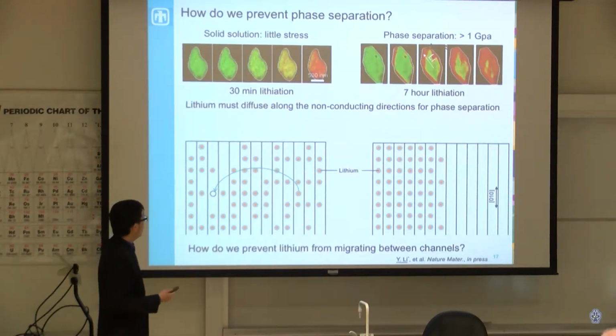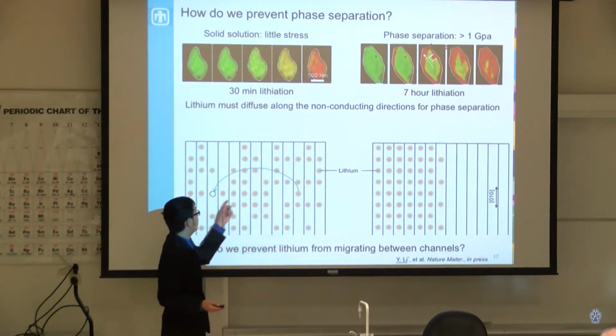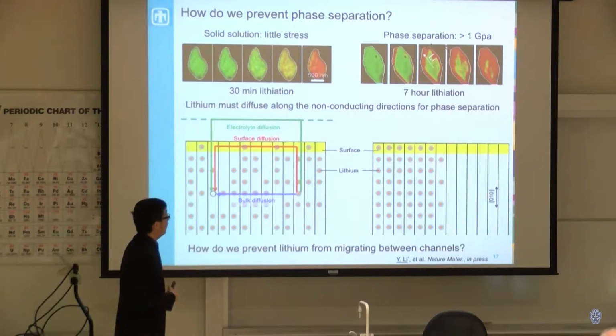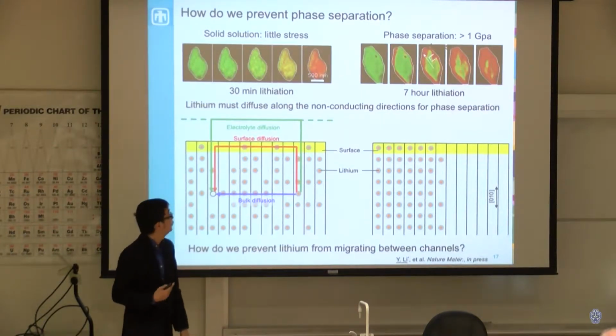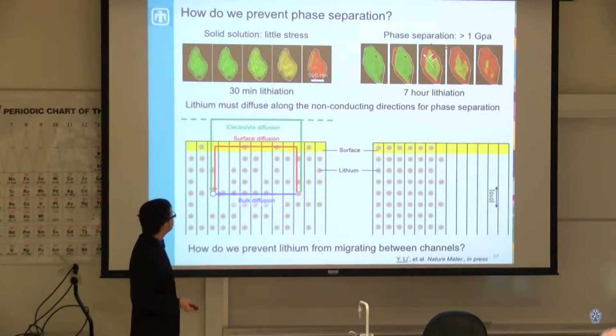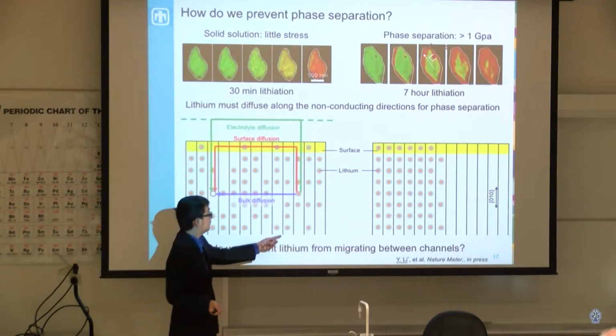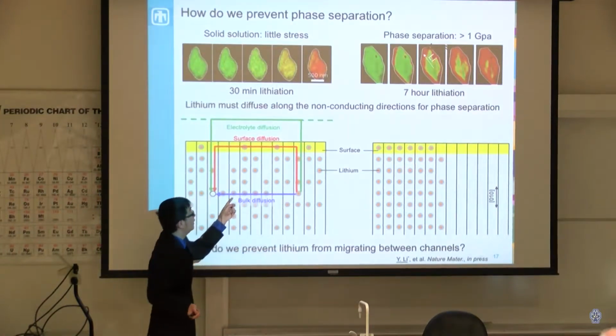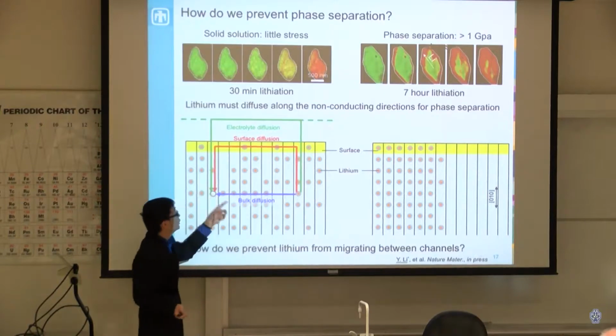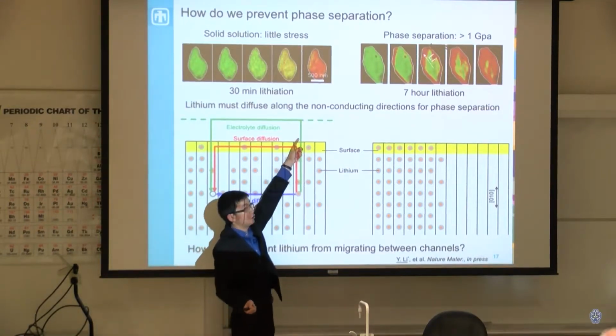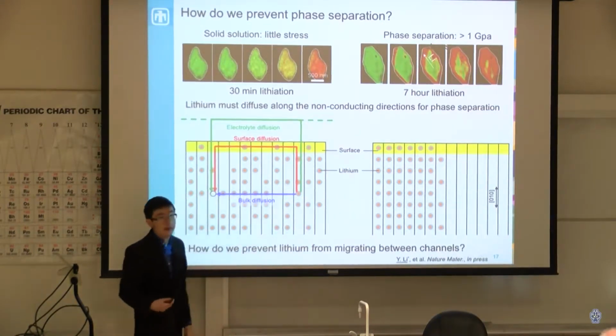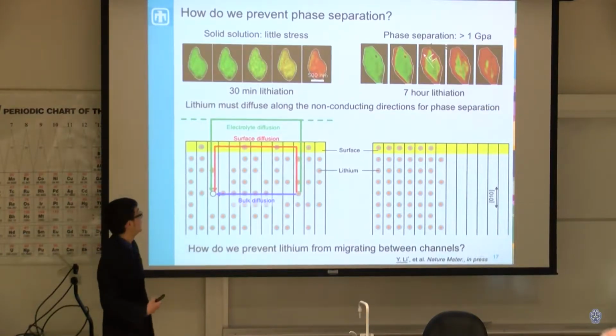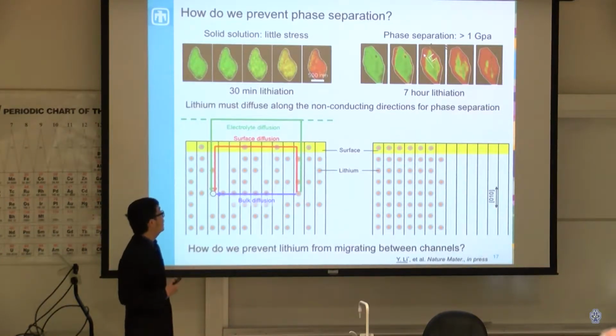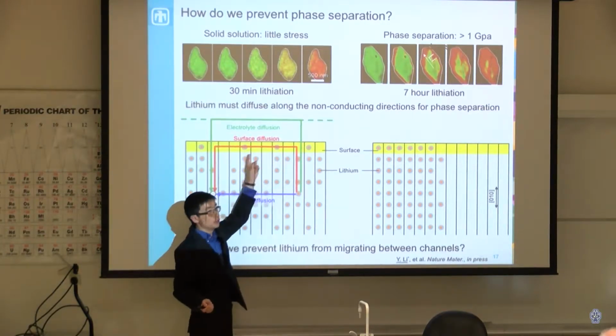So our goal is to understand how we can prevent lithium from migrating between channels. To make this quick, we realize that lithium can potentially migrate in the bulk, it can migrate along the surfaces, or it can go out of the particle altogether and migrate in the electrolyte. Our goal is to understand which of these pathways prevails, and without going into too much detail, the pathway that prevails is the surface diffusional pathway.